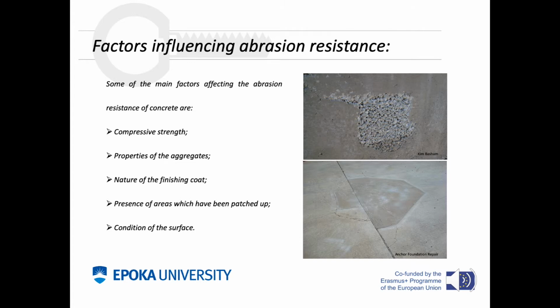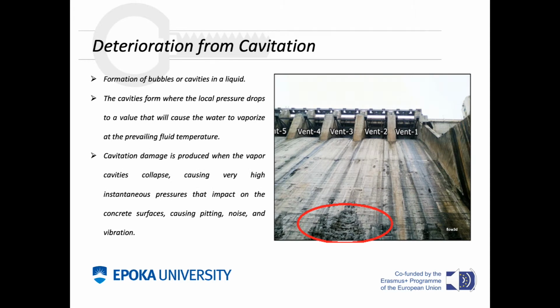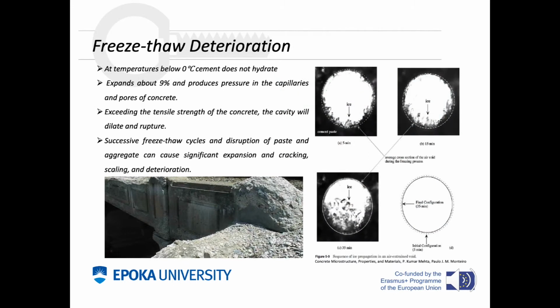Some of the factors affecting the abrasion resistance of concrete are compressive strength, properties of the aggregate, nature of the finishing coat, presence of areas which have been patched up, conditions of the surface, etc. Cavitation is the formation of bubbles or cavities in a liquid. The cavities form where the local pressure drops to a value that will cause the water to vaporize at the prevailing fluid temperature. Cavitation damage is produced when the vapor cavities collapse, causing very high instantaneous pressures that impact on the concrete surfaces, causing pitting, noise, and vibration.